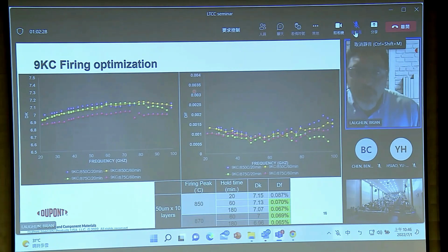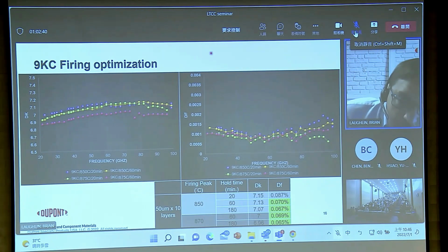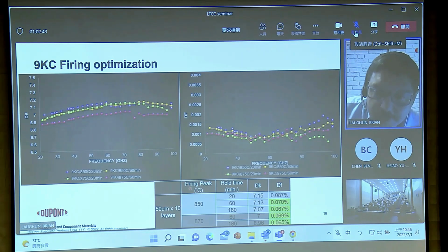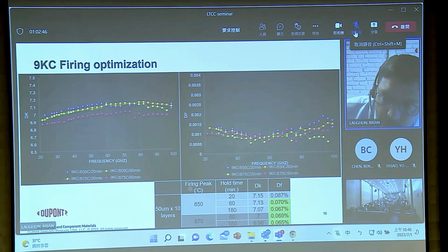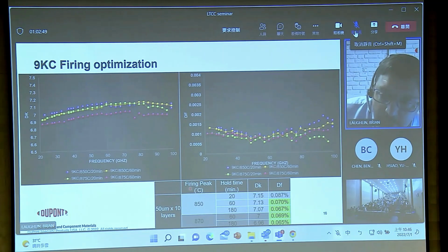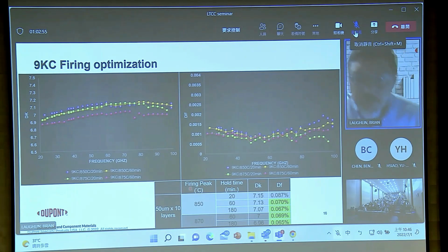And so just as an example, a lot of this data came out of Dr. Liu's lab. I would say there's two stories on this chart. So I show 9KC under different firing temperatures and firing lengths. So normally what we recommend is 850, 20 minutes, and you get what you'll see is the data sheet properties of DK and DF. And they're very, very good properties and very stable over a long frequency regime. But when you change the process, maybe even to extreme, from going from 20 minutes to 3 hours of a hold, you might change the dielectric constant a slight degree, or improve the dielectric loss a small increment.